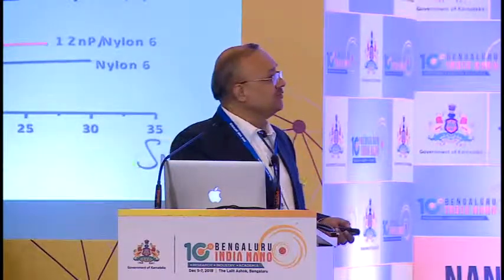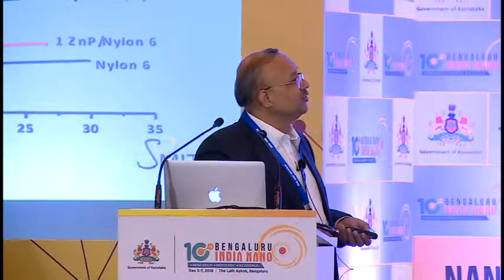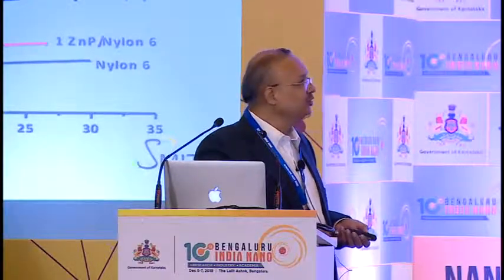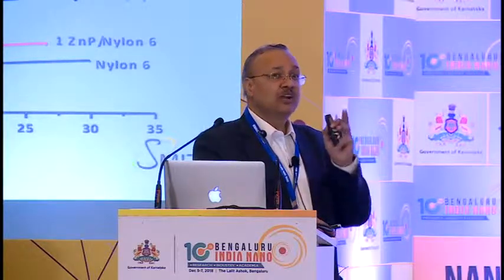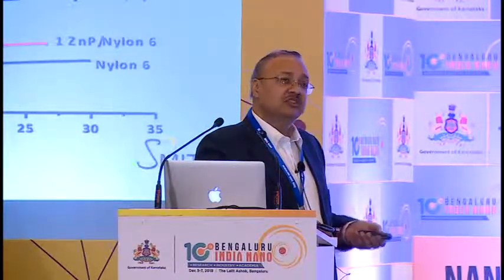And what happens to the properties? This is a tensile property. For a normal nylon 6, it's a commodity material which we wear. If you put particles, not much increase, and most of the literature is filled with this. We add nanomaterials, nothing happens, 10% increase, sometimes lower than that, less than the original values. You go to rods, there's a significant increase. You go to wires, there's an absolutely phenomenal change in the strength. Just don't pay attention to the strength. Look at the extension, how much this fiber can be extended. We have not sacrificed much on the extension.